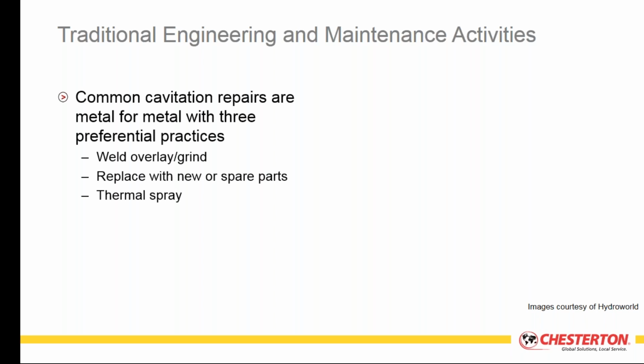The most common cavitation repair technologies are a metal-to-metal process where you're actually repairing the damaged metal with another metal, accomplished through a weld overlay and grind process. So you're welding on beads of metal onto the damaged area and then grinding everything flush and smooth. Another thing you can do is simply replace the worn parts. Obviously that has a cost impact and potentially a lead time and scheduling impact, so it may not be the first choice, but it might be an ultimate choice in severe situations.